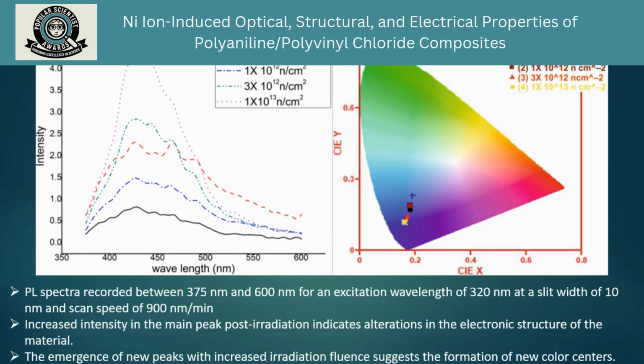It was observed that the increased intensity in the main peak after irradiation alters the electronic structure of the material. The emergence of the new peaks with increased irradiation fluence suggests the formation of new color centers after irradiation. The CIE color coordinates were calculated using GoCIE software and shown in the CIE 1931 color diagram.